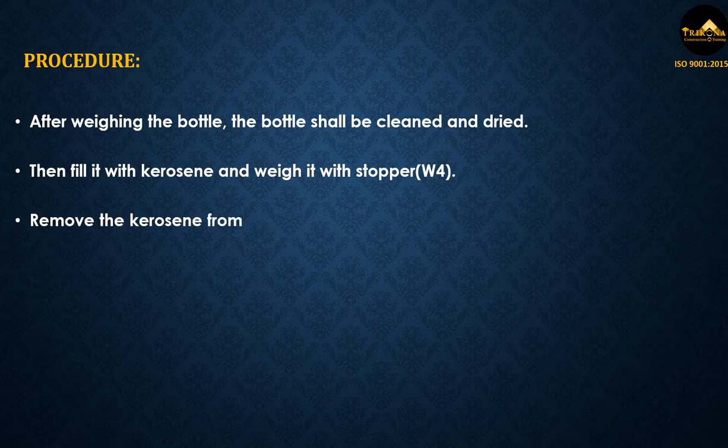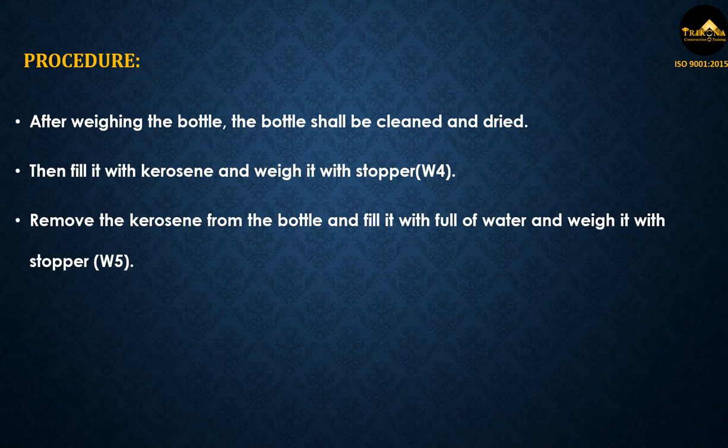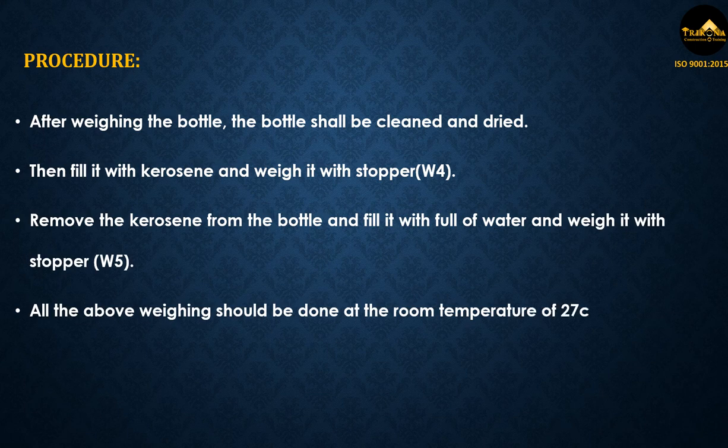Remove the kerosene from the bottle and fill it with water, then weigh it with stopper (W5). All weighing should be done at room temperature of 27°C ± 10°C.